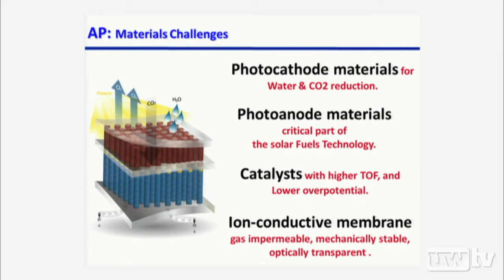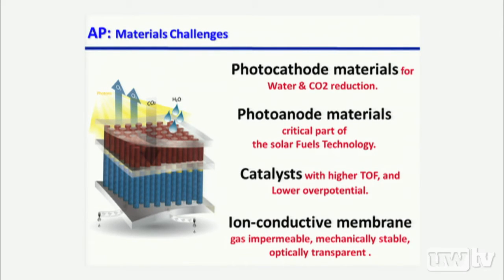By looking at this design, one would immediately realize what sort of materials are needed. So first of all, we need a photocathode. On the bottom side, that's the photocathode material for water and CO2 reduction. So in that case, you need a small bandgap material, that gives you enough photovoltage still, but you have to have suitable conduction band edge for those two reduction half reactions. Similarly, on the photoanode end, we need to develop a small bandgap photoanode with a suitable valence band edge.